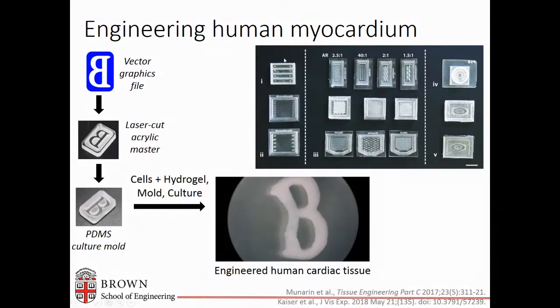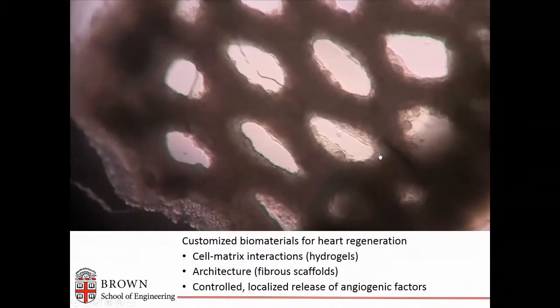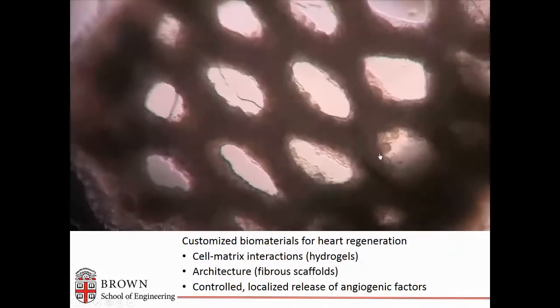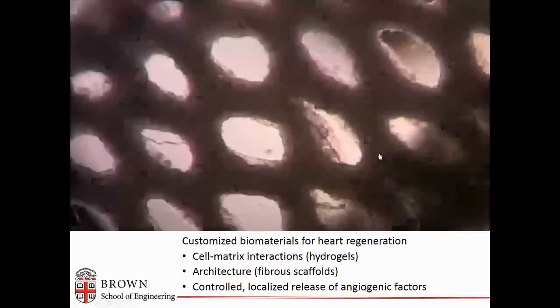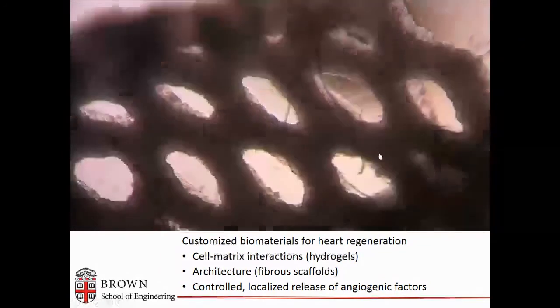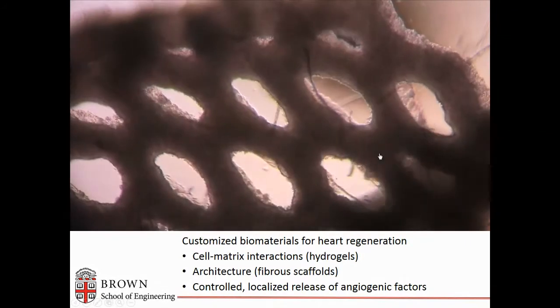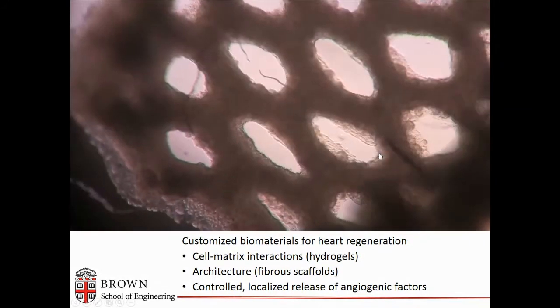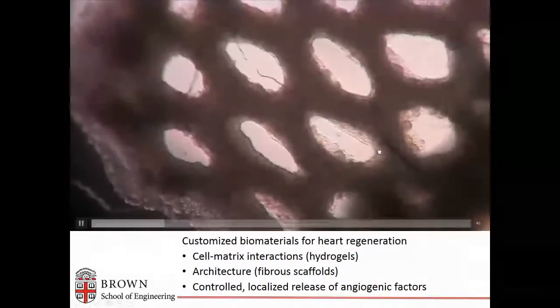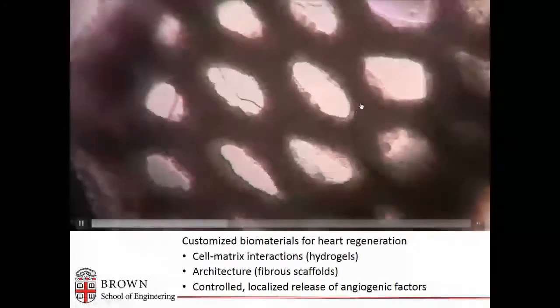This is from a paper that we published in 2017 describing this method, where we can make linear tissues if we're looking at mechanical measurements and force and contractility, or different designs for implant. This middle one at the bottom is what I'll show you that we've been using in our rat model of MI. This is an engineered tissue made from one of those molds, and it has 10 million cardiomyocytes in a collagen 1 hydrogel. They compacted the hydrogel and formed a syncytium, so a continuous electrical tissue, and it's beating spontaneously here. You can see the posts were elongated, and so they created these holes in the tissue.